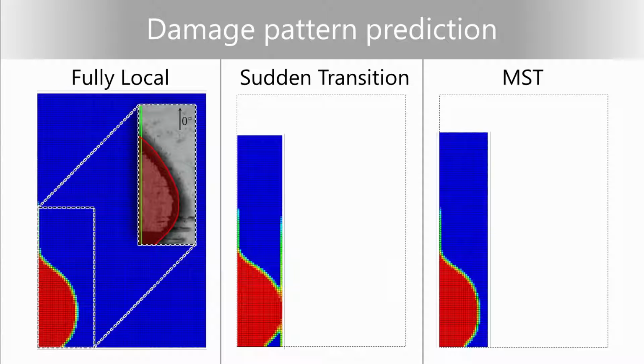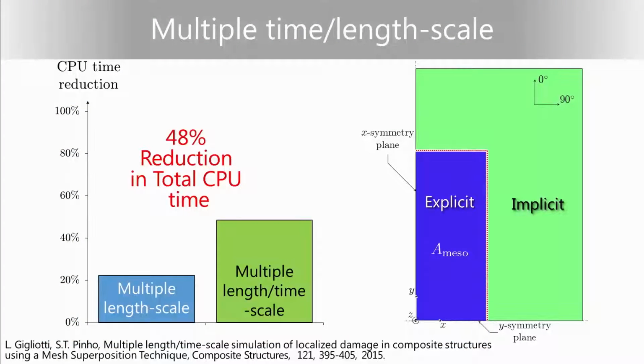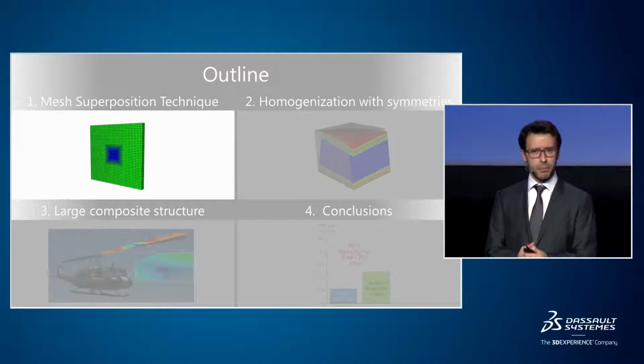Now, some of you could argue if we had a local model slightly bigger, the sudden transition model would still work. Now, of course, this would come at a computational cost. So the proper thing to do in terms of trying to measure the merit of this mesh superposition technique is to compare the computational cost of the most efficient mesh superposition model with the computational cost of the most efficient sudden transition model. And if we compare that, what we get is a benefit in terms of CPU time between something like 20% and something like 50%, depending on whether we only use an explicit solver or whether we use partly an explicit solver where we have damage and an implicit solver where we don't have damage. So that's a very significant improvement in computational time. So that's what I want to tell you about mesh superposition.